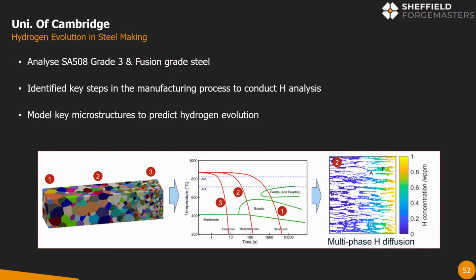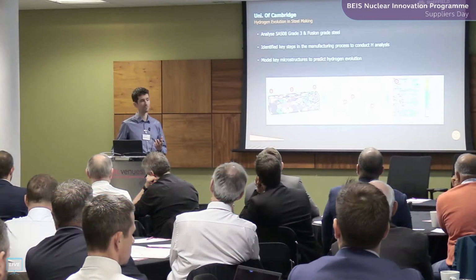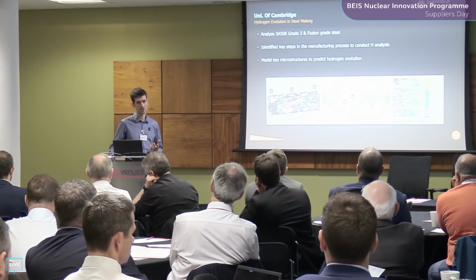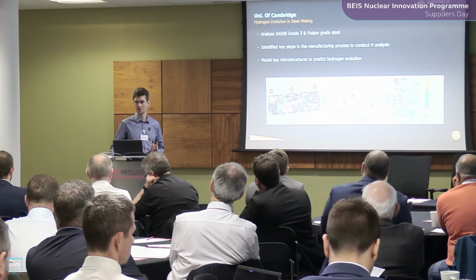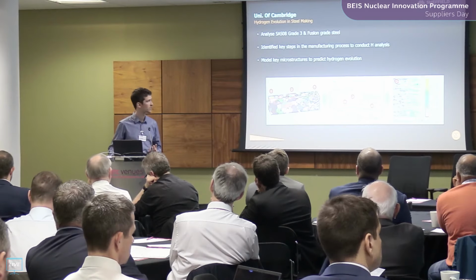It's really critical to bake hydrogen out of steels, as I mentioned. So Cambridge are looking exactly where that hydrogen sits, what mechanisms drive it in getting it out, and can we greatly reduce hydrogen bake out times, because for the large components we can literally have these components in a furnace at 650 degrees C for 2 weeks. So you can imagine the gas bill that generates. Okay.